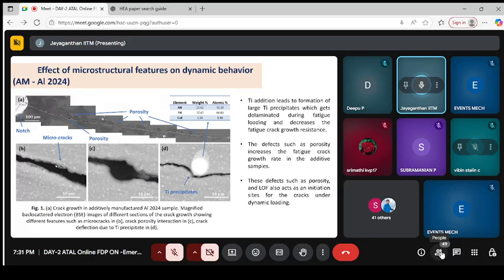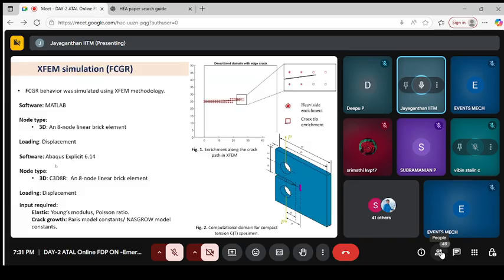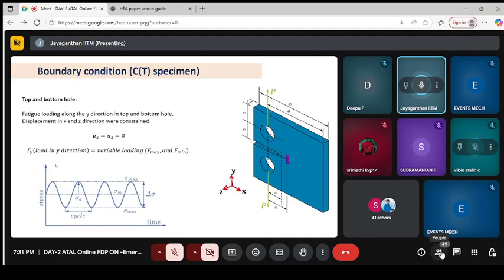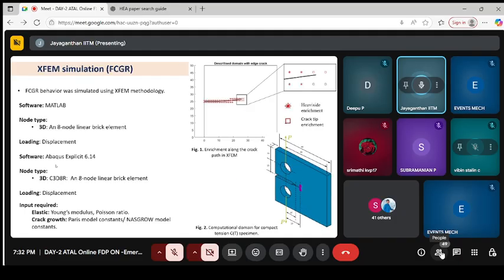Again, this is to highlight the internal porosity and how the cracks are moving. I will not go in depth into this particular micrograph. We have done XFEM simulation for crack growth movement, which we also characterized. Not only did we do experiments, we did thorough simulation also. The beauty of XFEM is that it takes up discontinuity in the material. For crack movement, you don't require any intensive mesh refinement. Remeshing is not required if you use XFEM.